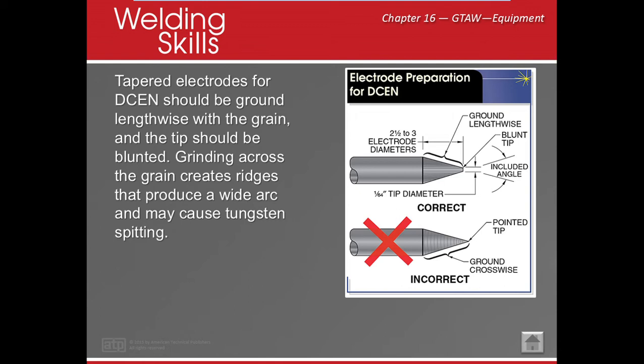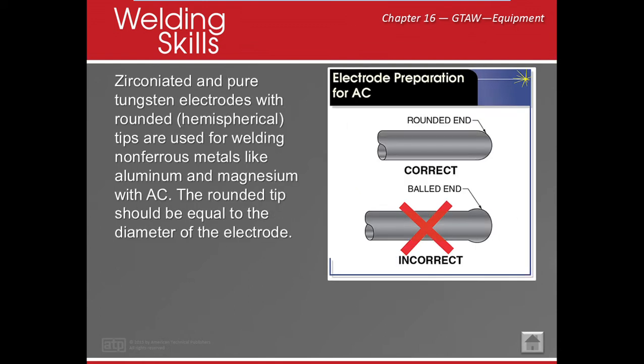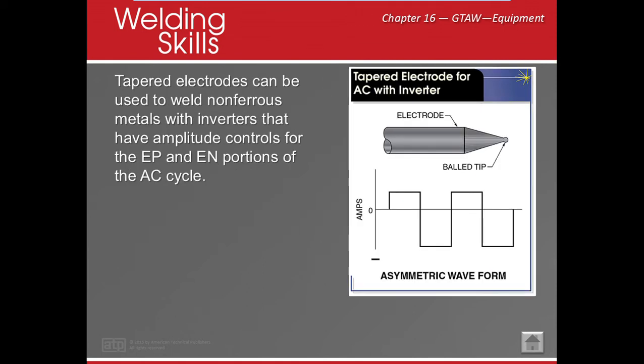We want to also avoid making the tungsten turn cherry red, okay? What can happen is it can melt the tungsten into like a little shell around the tip, and then when that tip and that shell get heated up when we're welding, a piece of the tungsten will actually fall into your weld and create tungsten inclusions, okay? So we know that the tapered tip is usually used for DC. Now, what about AC? Well, we want to use a rounded end, but as we get into the newer ages, we really don't need to. We can actually just have a tapered tip, and we can just knock off the top, okay?